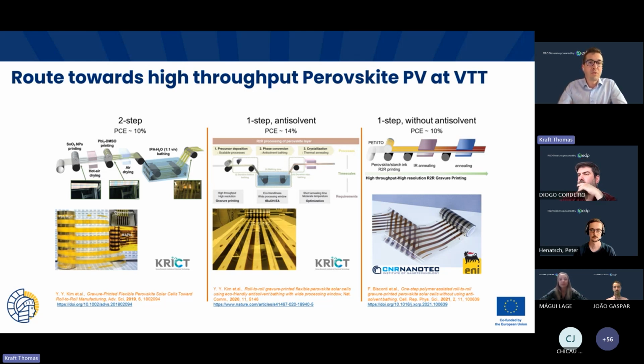Another approach we used was a one-step with an anti-solvent bath. So you print both precursors at the same time, and then it goes through an anti-solvent bath. Although these anti-solvent baths are not ideal, especially when you talk about volume manufacturing. So what we're trying to do is get away from that. So at VTT, we don't use any anti-solvent bathing, and we do a one-step approach. And in this case, we need to really have a very well-controlled ink and ink formulation to get that good crystallization and controlled crystallization growth of the perovskite during the in situ printing process.